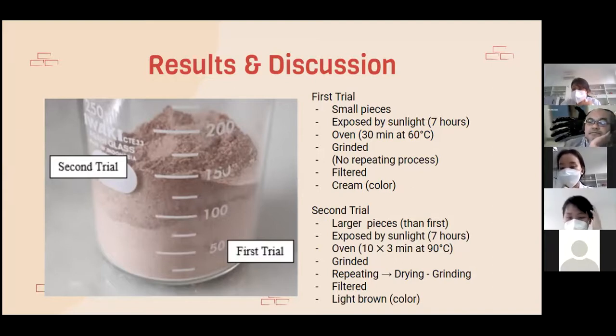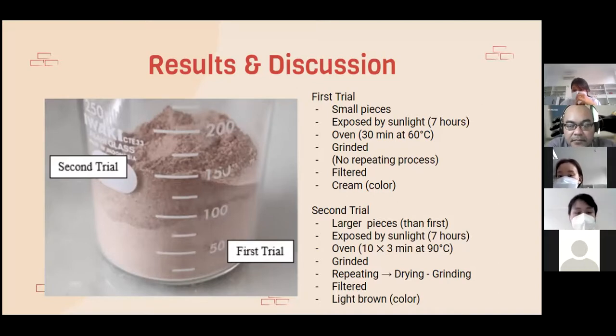After that, we ground it. The first one showed nice dried powder, while the second one was not. It was still moist, so we repeated the drying and grinding process until we got the dried powder result, and then it was filtered, and after that we got this result. The second trial is the darker one, due to overheating from the oven. Actually, the best way to dry natural materials is using 60 degrees Celsius.